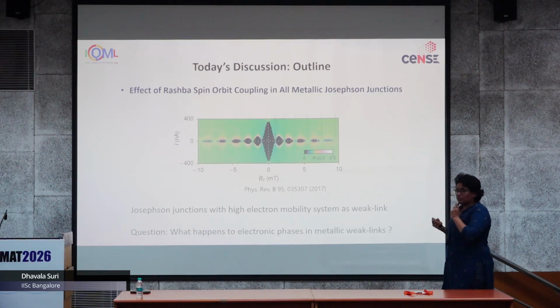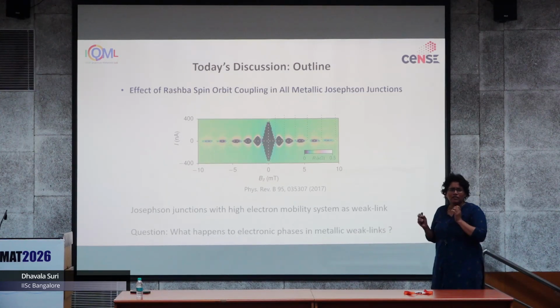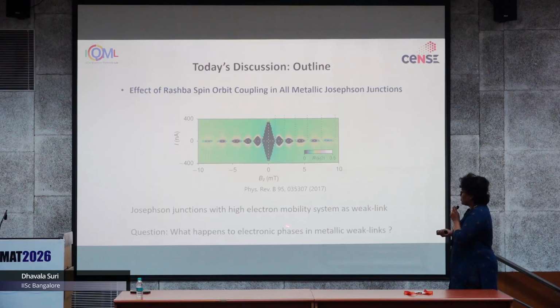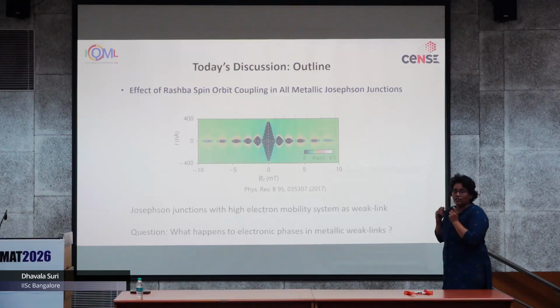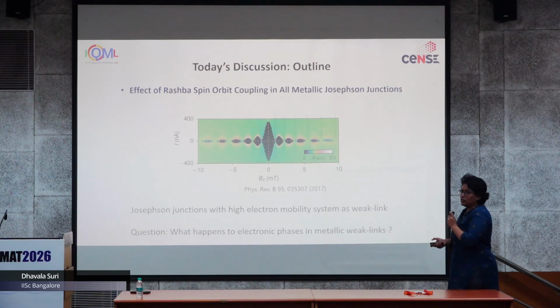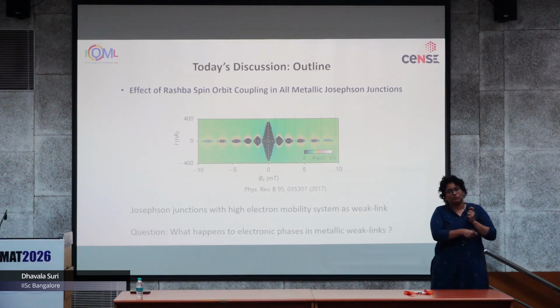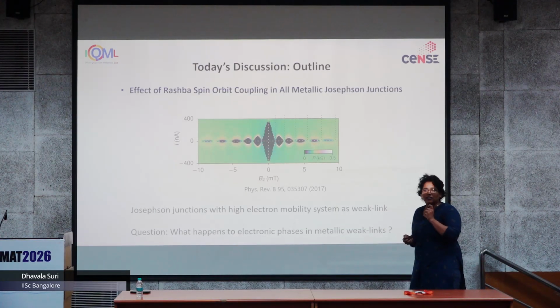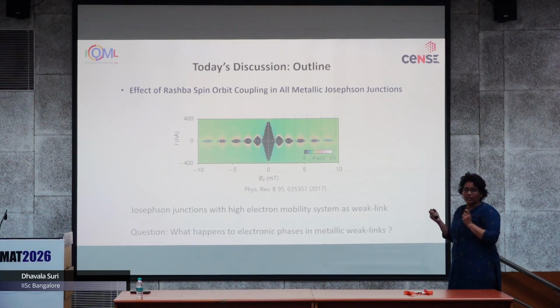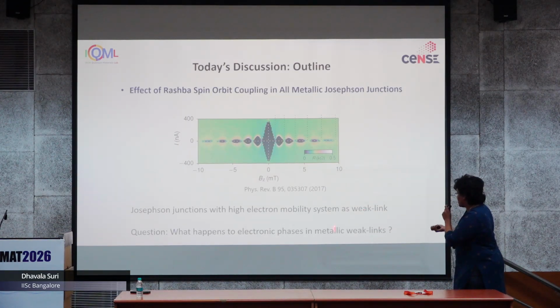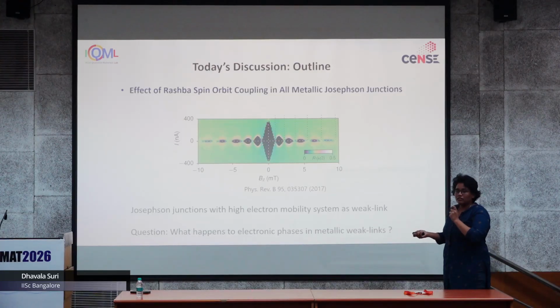Okay, and when you have such high electron mobility systems, it's relatively simpler to make Josephson junctions, given that the electron mobility is pretty large and there is not much scattering in the weak link itself. But there is a catch. If you try and go to III-V semiconducting materials all the time, indium arsenide or any such interface like GaAs and so on, you need an MBE to actually make these interfaces, and you actually need really high infrastructure to do all of this.